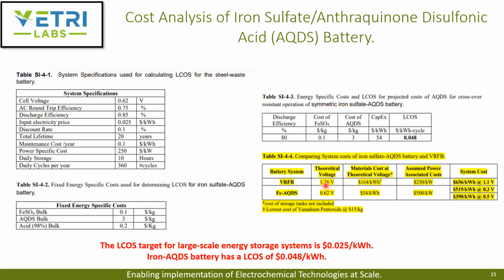And when you compare it with the best redox flow battery, which is the all-vanadium flow battery, the drawback is the overall cell voltage, right? The vanadium flow battery has a higher cell voltage, which is 1.26 volts, whereas with this you have only 0.62 volts. So this tells that you have to increase the number of stacks to get an overall voltage. Considering all that, they identified that when you operate at different voltage levels, your cost at least goes up by 2 times.